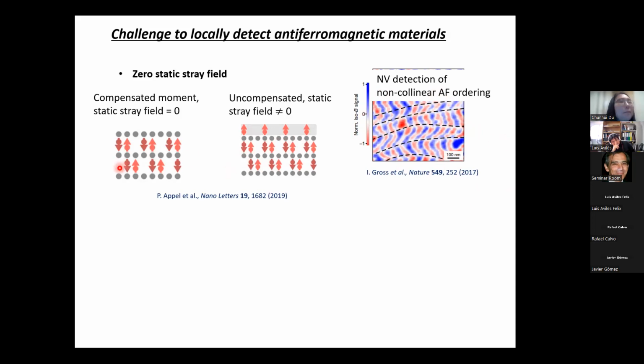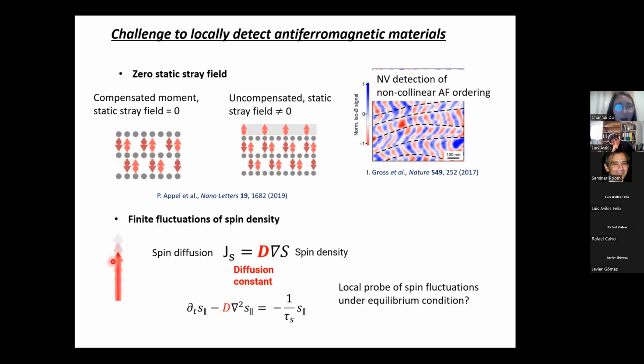So a fully compensated antiferromagnet has zero static stray field. However, it still allows development of finite spin fluctuations. So we can use NV center to measure the spin fluctuation and to study the antiferromagnet. If we look at the spin diffusion equation, the spin current is determined by the spin diffusion constant and the gradient of spin density. The spin diffusion constant is one of the very intrinsic spin transport properties, which is essential for us to understand the capability of the material to transport the spin current.